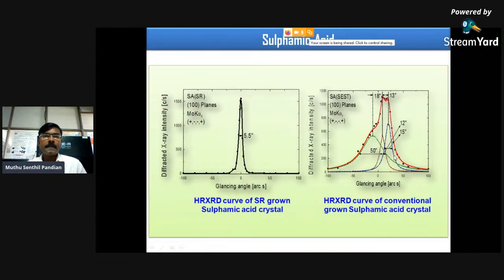I have also explained that due to temperature instability, a lot of solvent inclusions appear in the conventional method grown crystals. A lot of micro cracks and milky opaqueness appear in the conventional slow evaporation method grown crystal. Because of that, a lot of low-angle grain boundaries appear in the conventional method grown crystal. But in the case of the SR method, we have maintained the uniform temperature, so stable supersaturation, stable evaporation rate. There will not be any solvent inclusion or micro cracks or milky opaqueness in the SR method grown crystal. But there must be some dislocation. But compared to the conventional method, the SR method grown crystal dislocation is very less, that we can easily identify in the HR X-ray measurement and the chemical etching measurement.